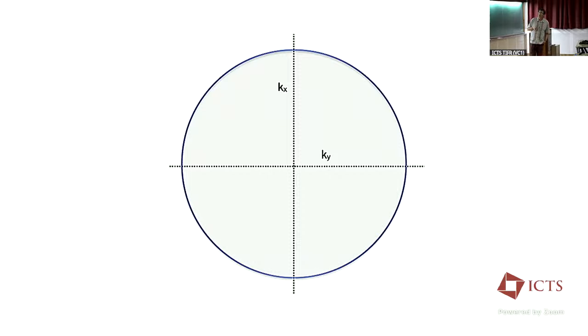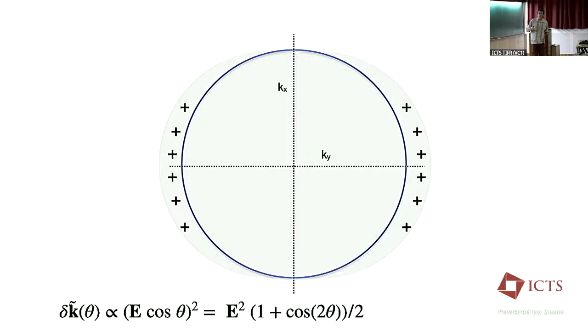Okay, so what happens now if we would use, let's say, multiple pulses to not just displace the Fermi surface sideways, but distort the Fermi surface in a different fashion? It's again a cartoon of what I imagine doing. You can imagine coming in with the Fermi surface and jiggling it back and forth, if you will, and leaving the charges high here and high there, but doing nothing here and there, right? So that has the perturbation of the Fermi surface. In the first case, the p-wave case, the perturbation of the Fermi surface went like E cosine theta, but this goes like E cosine squared theta.